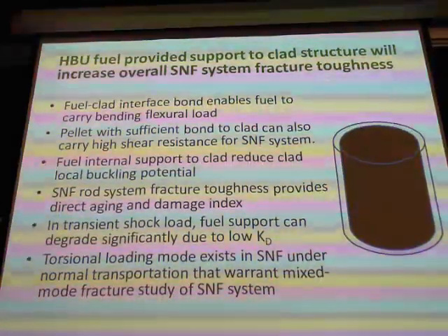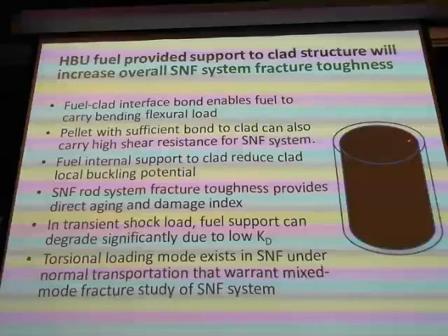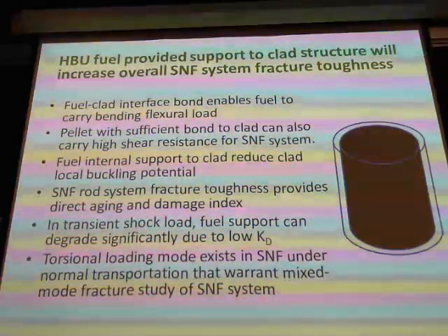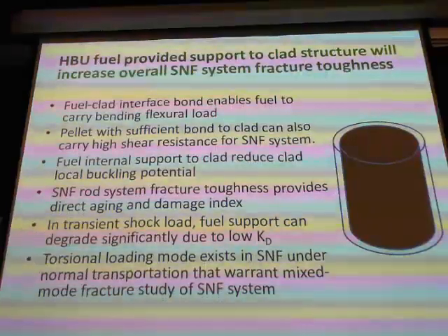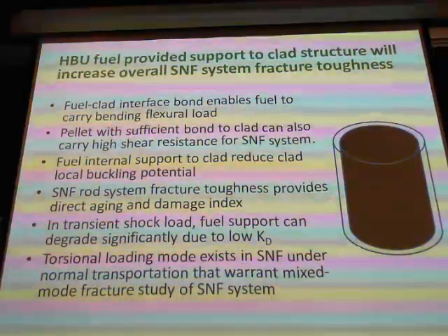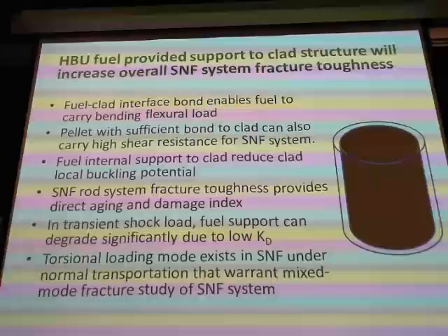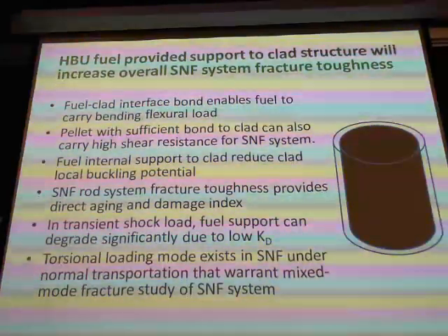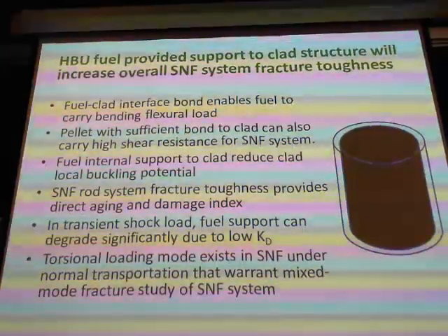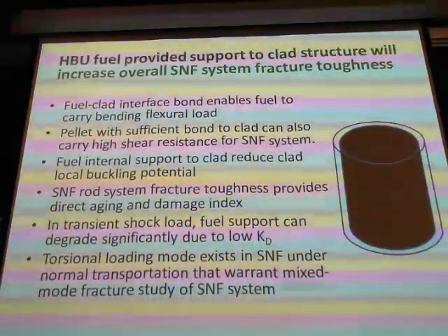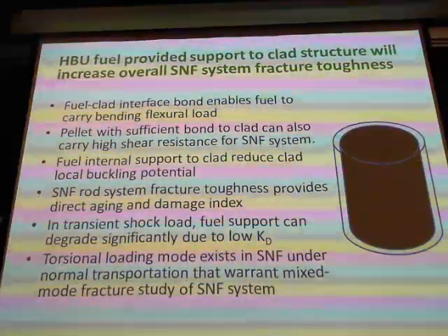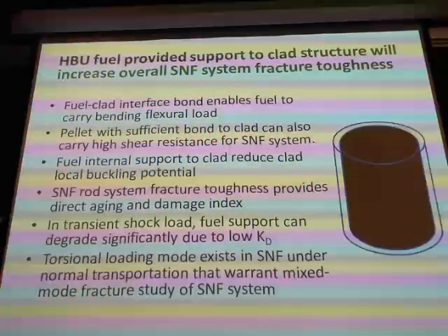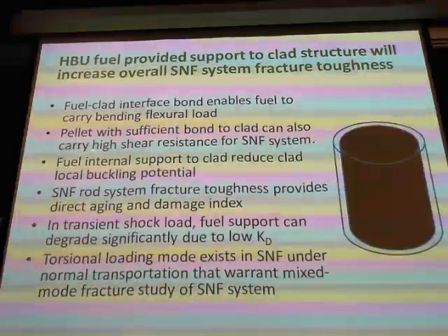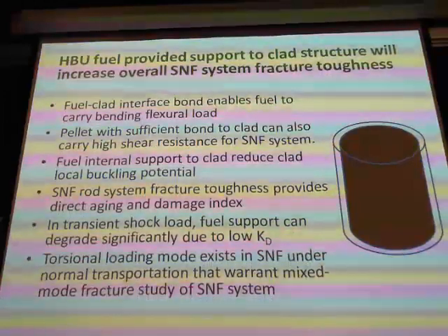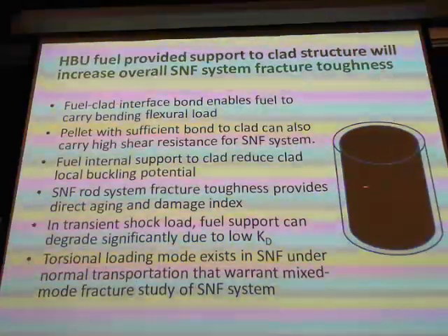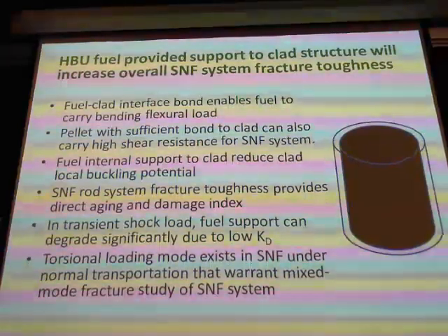This is a discussion, again, here. Now we have a plan, now we have a view. How do they interact? And Tom mentioned the interface bonding. This has really become very critical. And so, indeed, the fuel provides support. You can test any rod with a fuel. The bending moment resistance is very low, but you put a fuel in there, the resistance goes up significantly. And a pellet with sufficient bond to the clad can also carry shear resistance. Without shear transfer between the clad and the fuel, the two would not act together, would be separate.